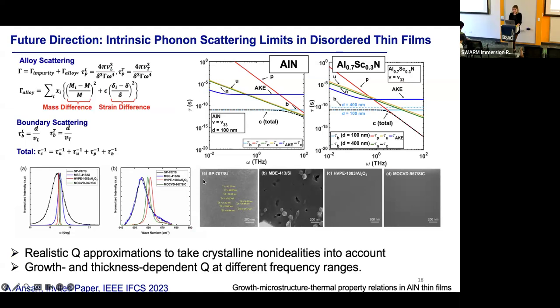I mentioned a few of them. For example, the grain boundary size becomes different. The thickness itself plays an important role. And in the case of aluminum scandium nitride, we have alloy scattering that is added due to the mass difference and the strain difference when introducing scandium in your aluminum nitride lattice. So this is something that I think the entire field still lacks: more realistic Q estimations based on all the non-idealities or the specific material properties in the thin films.